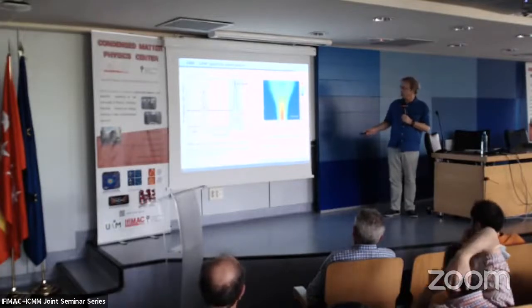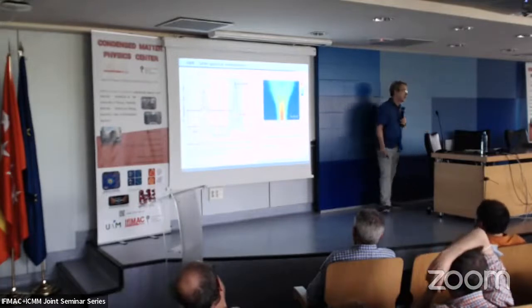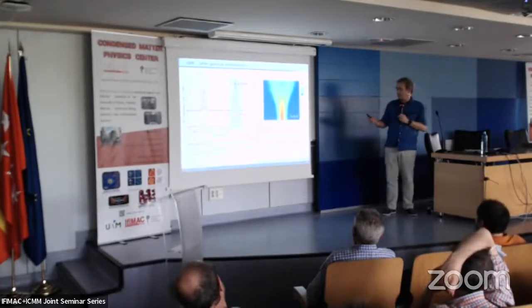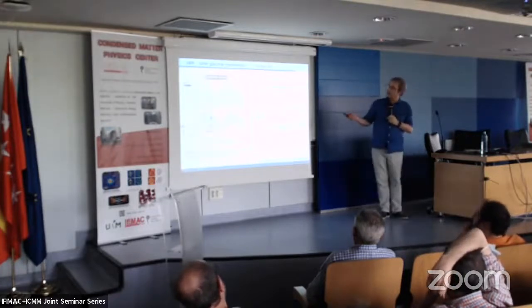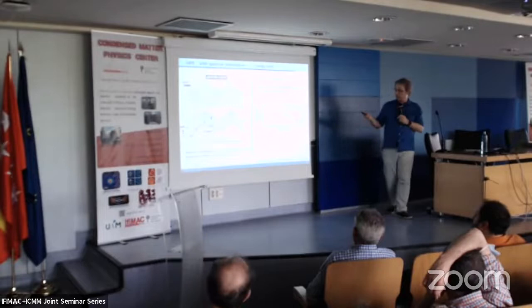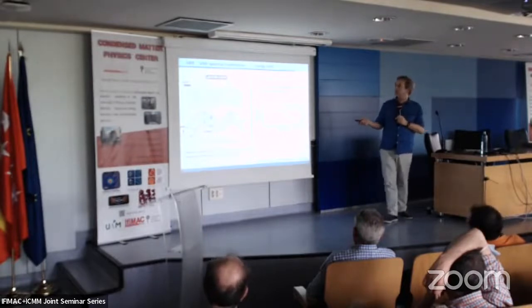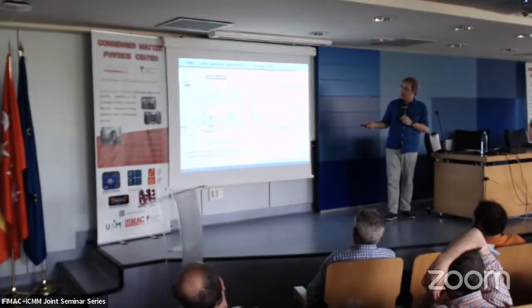And this splitting in this case is 1.1 milli-electron volt, and we can go up to 2.5 milli-electron volt. This periodic strain, tension and compression, has an effect on the band gap. The band gap, in this case, is not really a band gap, but the gap of the defect. So the energy differences of the defect are modulated by the periodic strain which is applied.